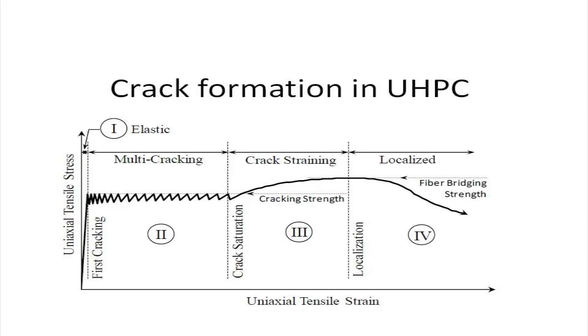UHPC is also distinguished by steel fibers, which make up about 6.2% of the material by weight and help make it slightly more ductile, resisting stress by deforming in place of the concrete itself. UHPC has significantly better mechanical behavior than regular concrete, retaining much of its tensile strength even after cracks first start forming. In addition to an elastic modulus two to four times harder than traditional concrete and a compressive strength of up to 200 MPa, UHPC is significantly more resistant to fatigue. In lab tests, a concrete girder being tested for use in highway bridges was able to withstand 12 million load cycles without significant fatigue degradation or change in overall mechanical behavior.